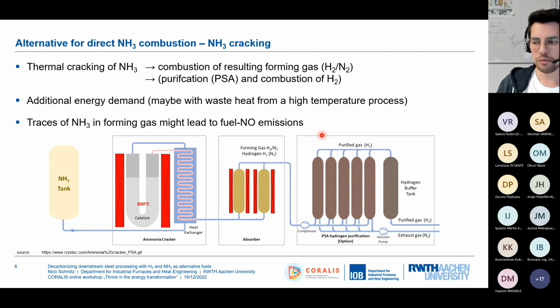We have to keep in mind that we have an additional energy demand here to crack the ammonia. We need a temperature of about 750 to 1000 centigrade and a catalyst. But in our plants, we mostly have high temperature waste heat. So maybe it could be an option to create some symbiosis and put the ammonia cracker in the off-gas system of the high temperature process, to have the ammonia cracked partially or completely and combust it in the furnaces, because we have really good waste heat potential in most of the furnaces.